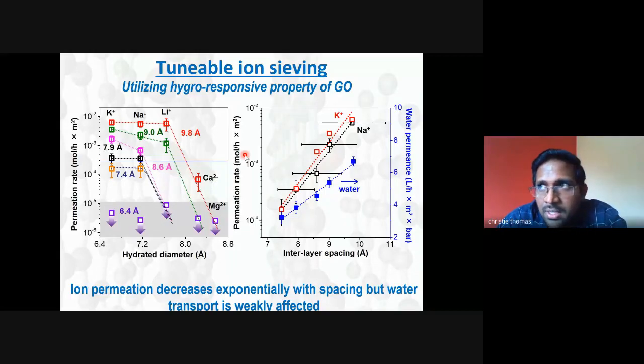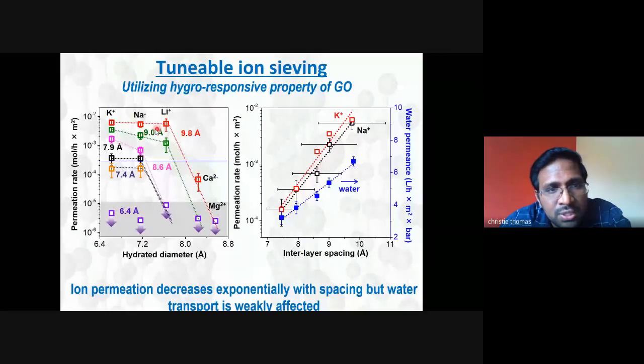There are a lot of studies already undergoing on chemically restricting the swelling, using different functional groups. We use physical restriction. The most important point here is what we observe once we restrict the swelling. On the left-hand side, you see different capillary sizes: 9.8, 9, 8.6, 7.4, 6.4 angstrom. So we made graphene oxide membranes having different capillary sizes. How did we make them? By controlling the RH, we can tune the d-spacing, and then by physically confining, we can keep that capillary size.